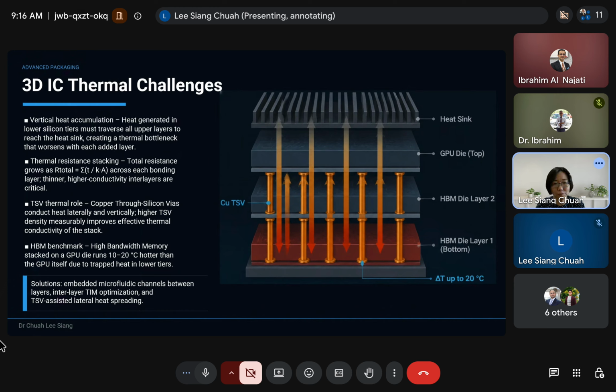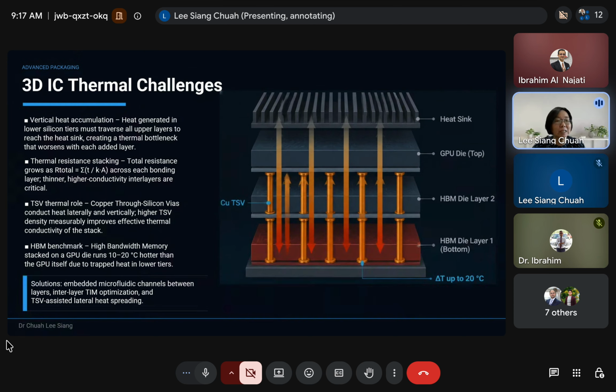Through-silicon vias help by providing vertical copper paths that improve the electrical and also the thermal conduction, increasing the effective heat spreading across the stack. In practice, even in modern HBM-stacked GPU systems, the memory layer can run 10 to 20 degrees hotter than the GPU die due to the limited heat escape. To address this, researchers are developing microfluidic interlayer cooling, advanced TIM, and high-density TSV thermal networks, some of which are already moving toward early deployment.